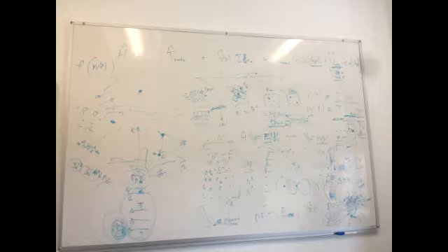So it basically means 1 in 10 atoms. So you need at least 10 unit cells to describe these materials. And because of 3D structures, maybe you need 30 unit cells. So now, instead of calculating the system for 1 unit cell, you need 30 unit cells. And again, we said it scales as n squared. That's why this space is not really being calculated.